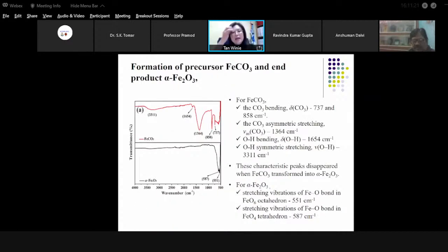These are some of the characteristic peaks shown by the precursor iron carbonate. Then the characteristic peaks disappear when the iron carbonate transforms into hematite. The hematite is indicated by the presence of peaks at 551 and also 587, which correspond to the stretching vibrations of the iron and oxygen bond.